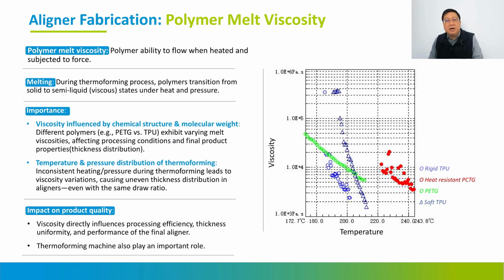To make a good aligner, there are two important factors. Even on the same processing machine, with the same pressure and the same temperature, different aligner materials show different thickness distribution, because their melt viscosity behavior is different. So I will show this diagram. If we use a multi-layer, it is a kind of compromise of the two kinds of material, so we make the thickness distribution more even. Later on, another colleague will show all the data in another chapter.